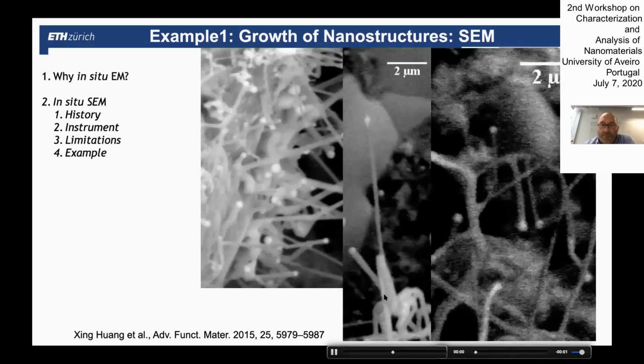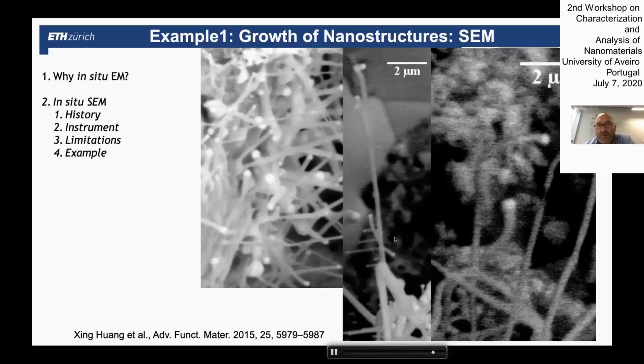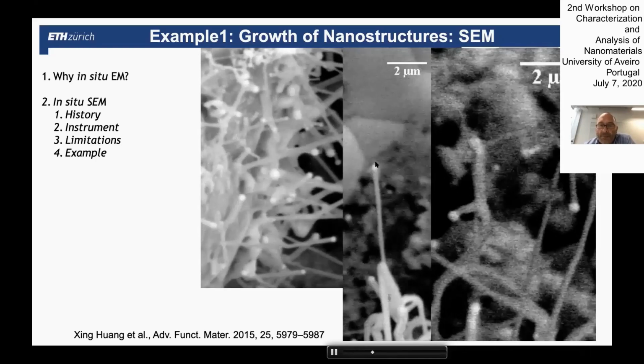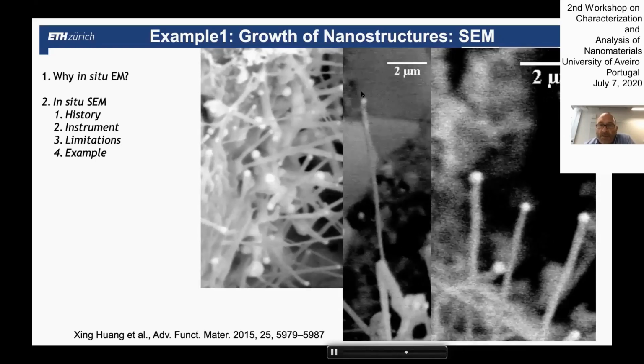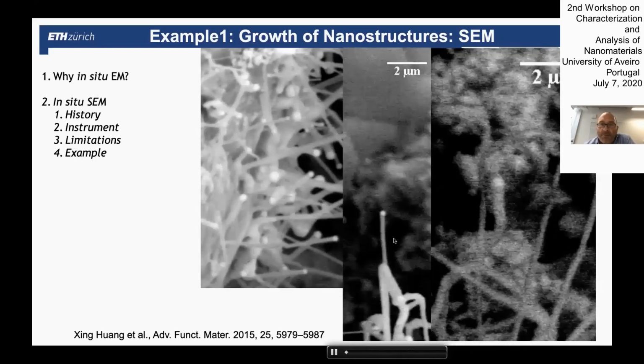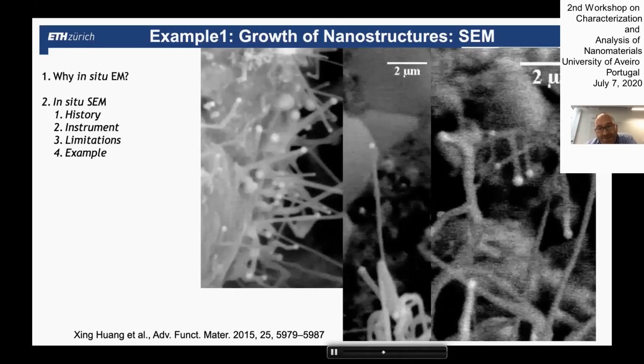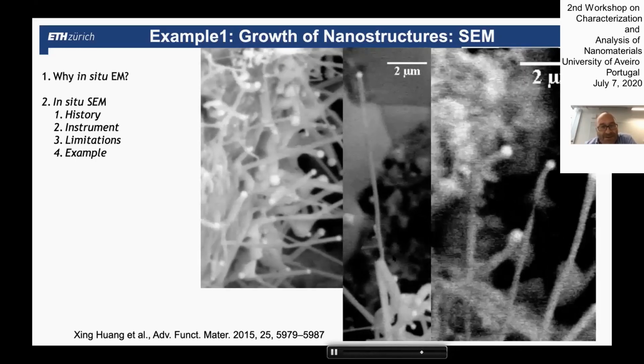This growth that you see here is a vapor liquid solid growth. There's a vapor phase because of the vaporization of the cadmium sulfide and the zinc sulfide, and the vapor then condenses on these silver nanoparticles, and from there you have a vapor liquid solid growth. This is what you see in the SEM.